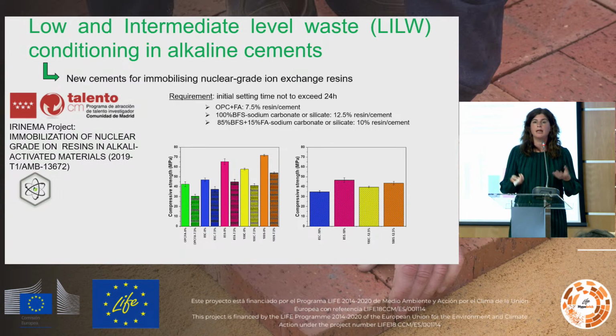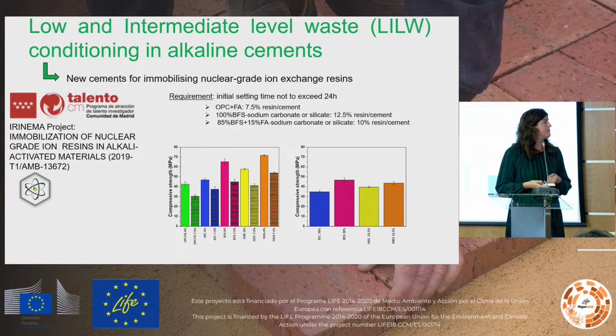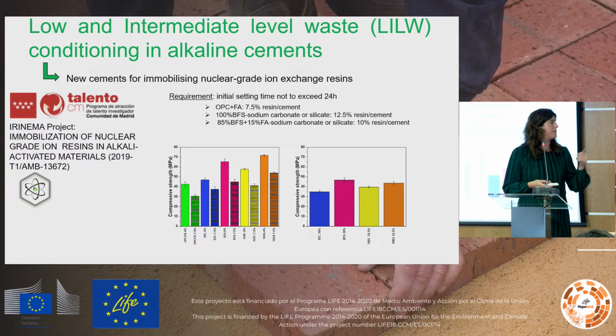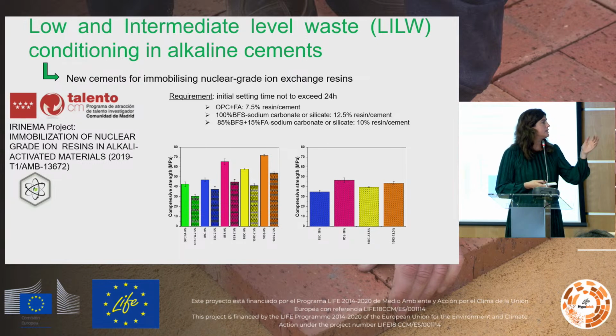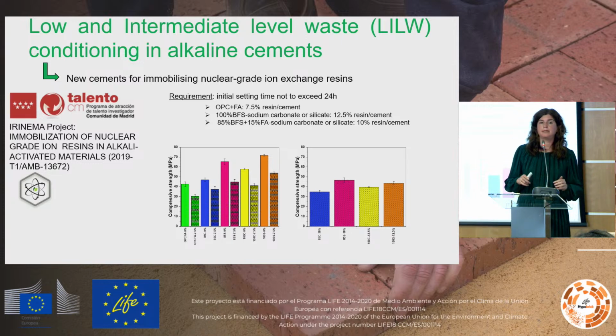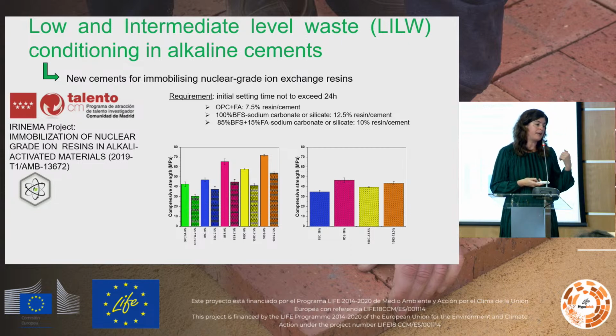In all of these studies, we can see that all of these materials can immobilize a higher content of resins. In the first slide, I wanted to show mechanical resistance of the reference matrix, that is cement, with 7.5% of resin and cement. And you can see how mechanical resistance ends up being higher. I also wanted to show here this graph in which we have included the maximum amount we can immobilize, taking into account a few prerequisites, and we can see that it goes over 10 megapascals as a limited value to immobilize this kind of radioactive waste.